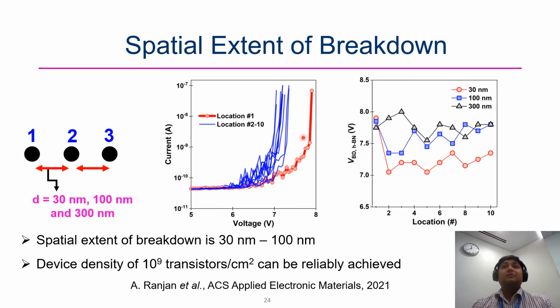So what we see here is that the first breakdown has a higher voltage compared to all others. So what does it mean? That the extent of the first breakdown site is large enough that all the subsequent breakdowns we are doing are in close proximity. So it's definitely more than 30 nanometer.